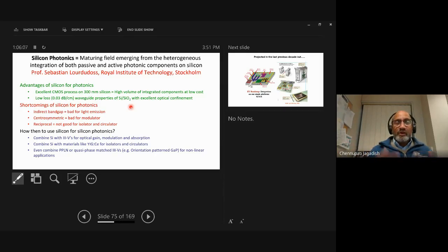Though silicon may not be very good for light emission applications, silicon could be used for modulation, and also for waveguides, multiplexers and demultiplexers, and silicon dioxide combinations. Most recently, people are also using a lot of silicon nitride, and silicon nitride based devices are showing even lower losses, which is an exciting development. So really, there are some things for which you cannot use silicon. I mentioned that it is an indirect band gap semiconductor, which means you cannot use it for light emission, and it is centrosymmetric, so it's not very good for modulators.